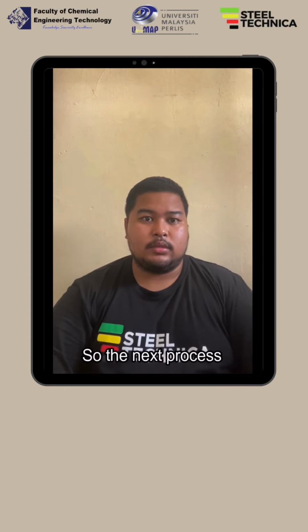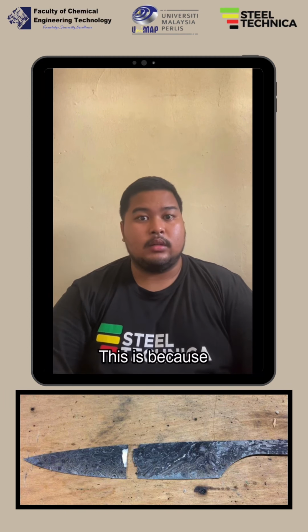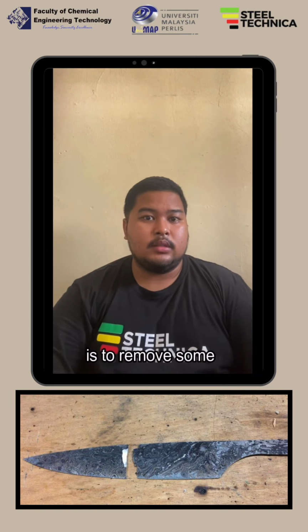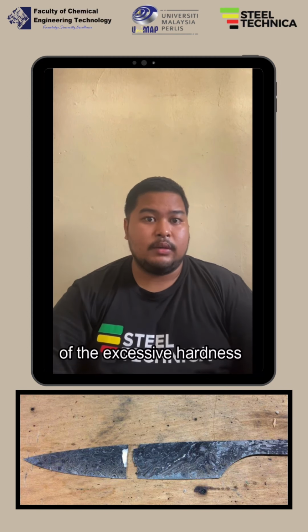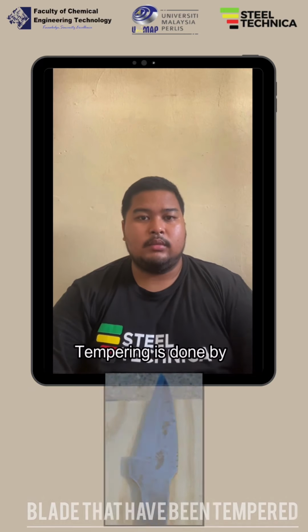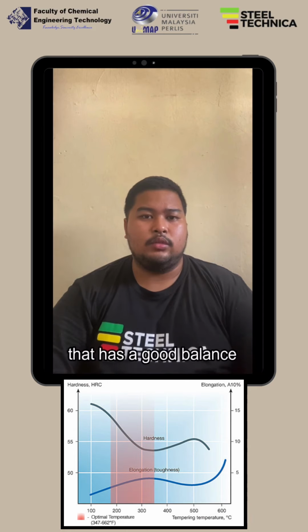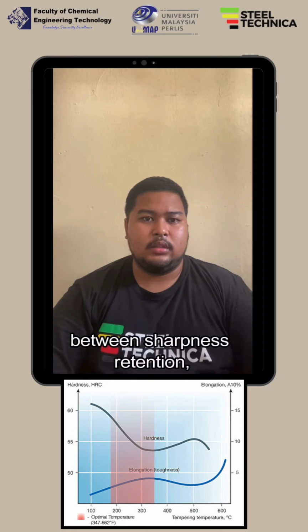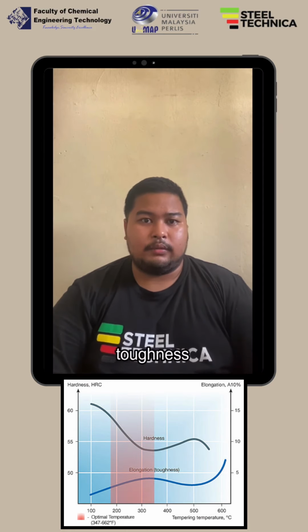So the next process is tempering. Tempering is a very important process in producing a durable knife. This is because the purpose of tempering is to remove some of the excessive hardness of steel. Tempering is done by heating the blade to 175 degrees Celsius for two one-hour cycles and letting the knife cool between each one. This is to get a knife that has a good balance between sharpness retention, grindability, and toughness.